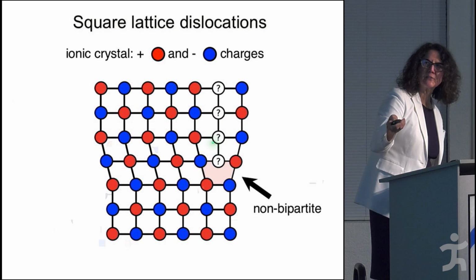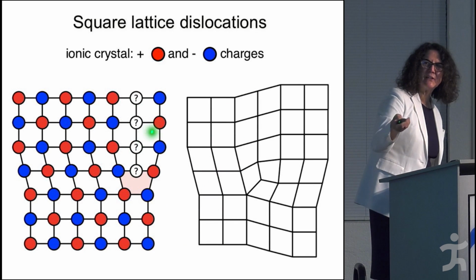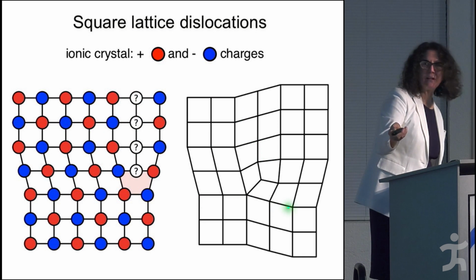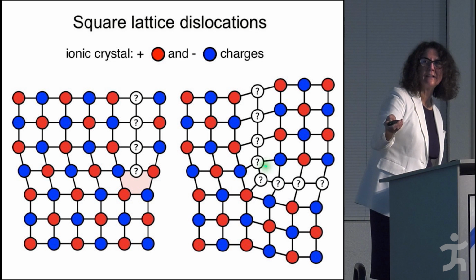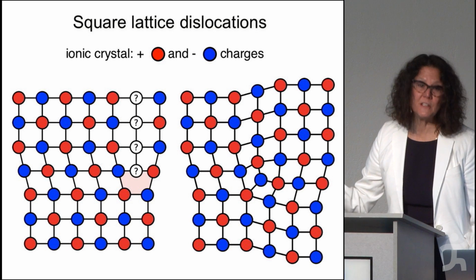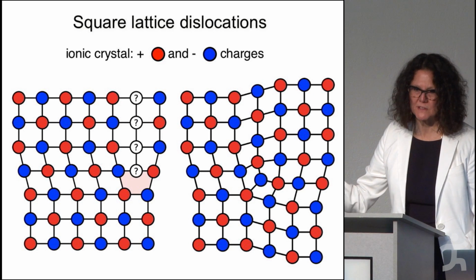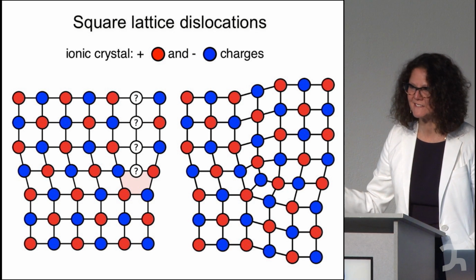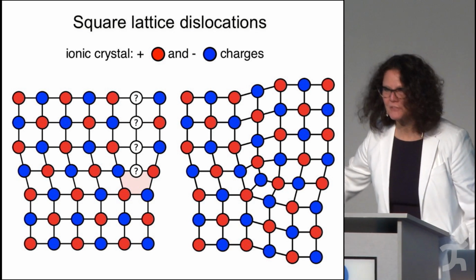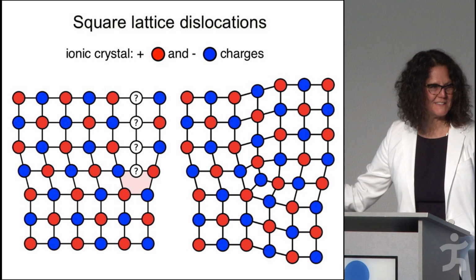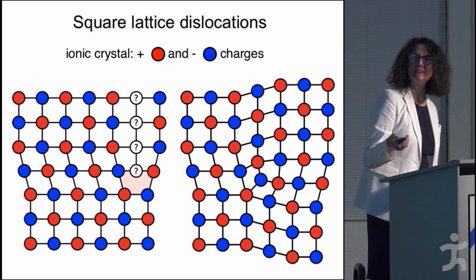What is the line of defects you put here? You can't. Because if you put here, say, red, you are violating the red. And if you put blue, you are violating that. So in order to have a defect, you have to pair with another more complicated defect. And so it's very difficult to actually close these things in a sphere. And this is just, again, from another point of view, so it matches the results we find.